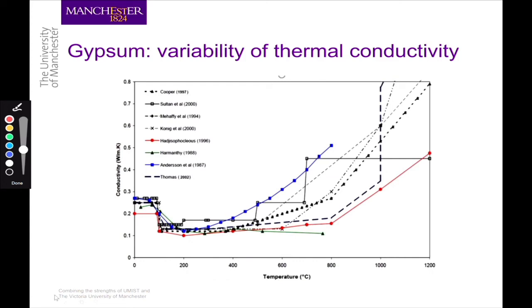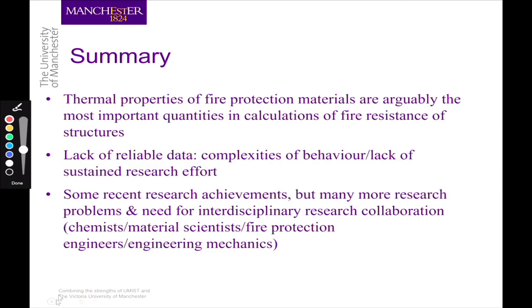And of course, another issue with gypsum is the variability of thermal conductivity. I have explained the basis of one model which we have used to quantify the thermal conductivity temperature relationship of gypsum. But there are very many models, there are many theories about the thermal conductivity of gypsum, why and how it changes as a function of temperature. And these are the models which we have collected from literature. As you can see in here, there's really a big range of values. How do we deal with this uncertainty? Of course, which one is actually the best one, the most accurate one? But if we can't solve that problem, how do we deal with this uncertainty? That, of course, is an issue as well. That depends on the structure you're dealing with. So there are still a lot of issues in here.